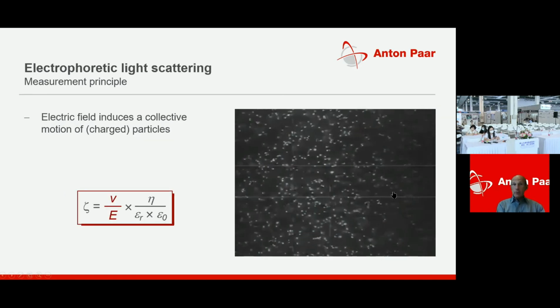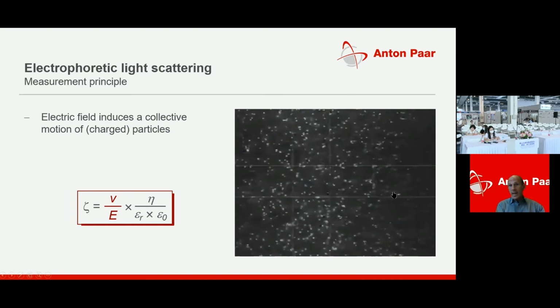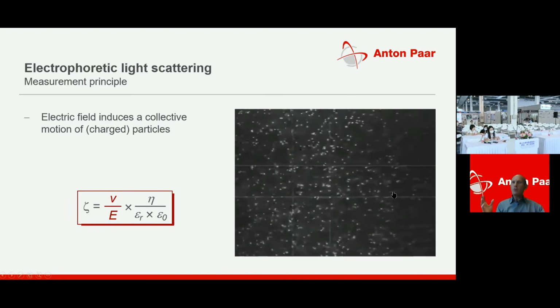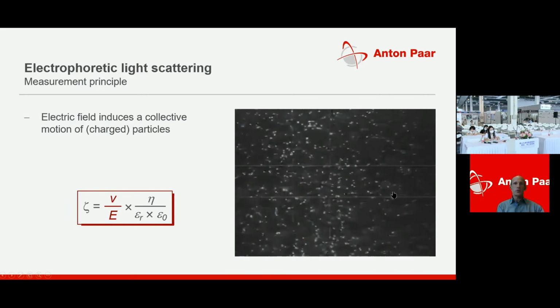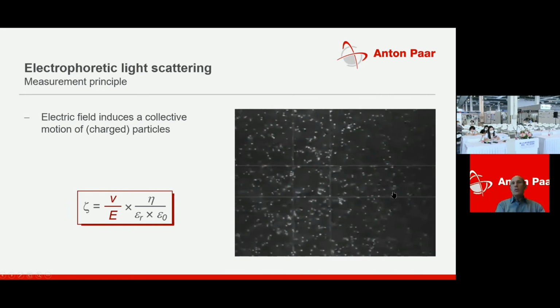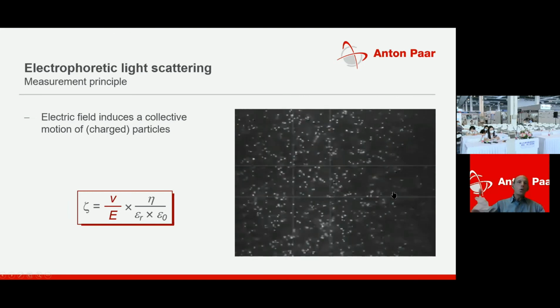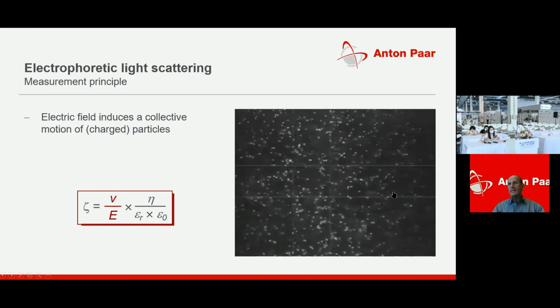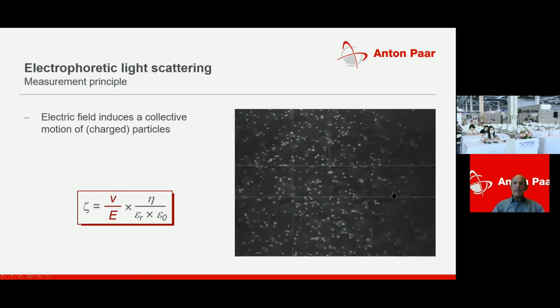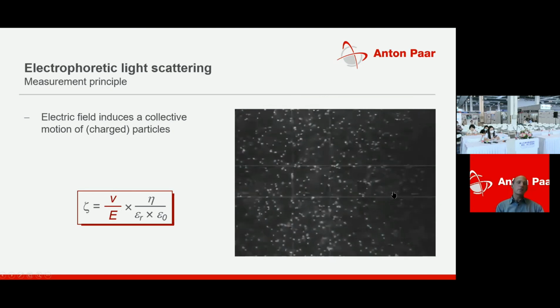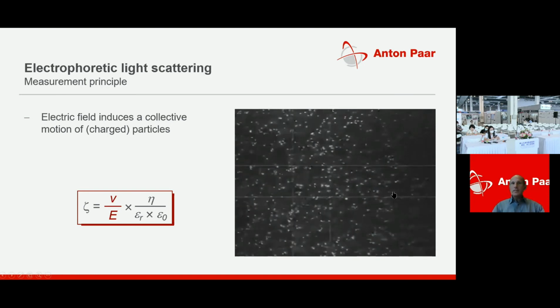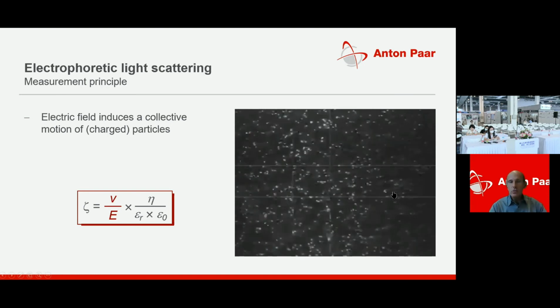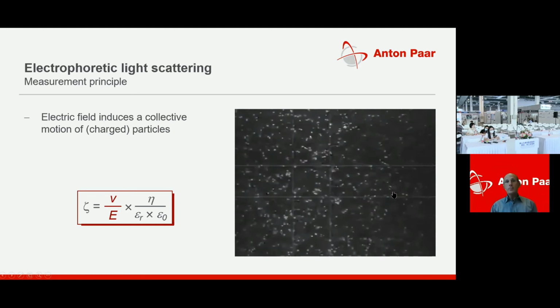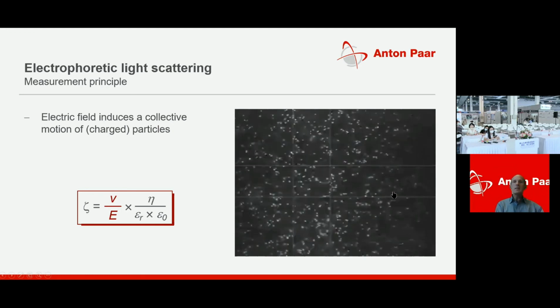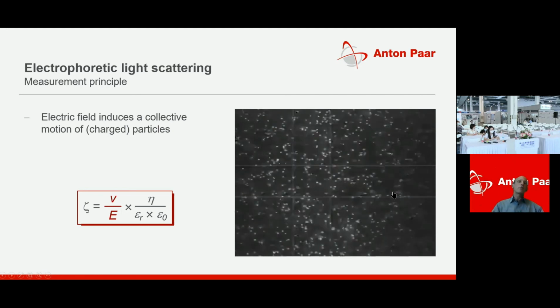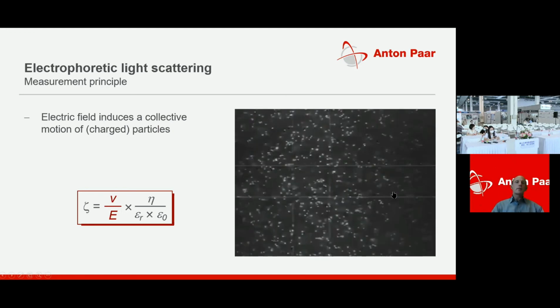In electrophoretic mobility or electrophoretic light scattering, we apply an electric field on the nanoparticle dispersion. The particles move according to their net charge, either towards the positive electrode if they are predominantly negatively charged, or to the negative electrode in case of positively charged particles. In electrophoretic light scattering, the electric field is reversed, but at a much higher frequency, as you can see in this video, recorded for a microelectrophoresis experiment using an optical microscope.